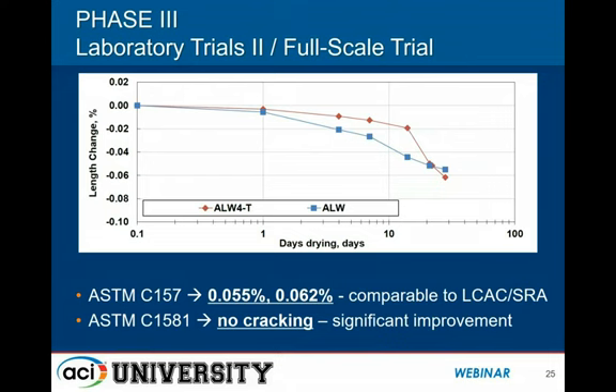And we weren't really quite sure what we would see in terms of benefits, but the CAC responds differently as a cement during the hydration process when it has water available. It tends to vastly change the early hydration kinetics. And what we saw was a little bit of a reduction in the speed of early strength gain, but not enough that it really worried us from a field standpoint. But we did see a tremendous improvement in crack resistance. So we had no cracking at all in these rings.